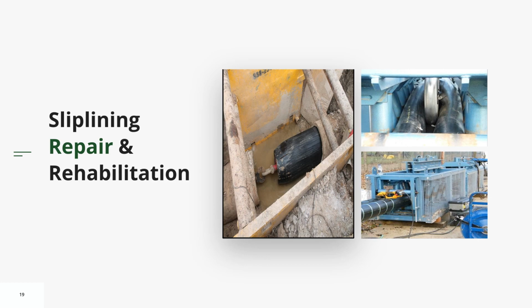And so here on the right-hand side, again, we've got the fold down. In the top right, you're folding it down, and that's high-density polyethylene pipe. And then you see it coming out of that machine folded down. They put straps on it or just tape on it about every 400 millimeters. And then you introduce it to the host pipe. You seal off both ends of it. You put air pressure onto it, 5 or 10 pounds, and it causes all those bands to pop. The pipe pops up and back into its circular shape, and you've now got a new pipe in.